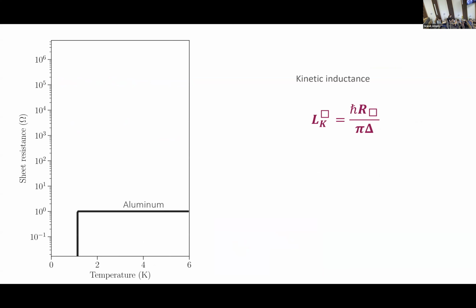Okay, now let's try to get a little bit of a sense about this quantity in terms of values. Here, what I show you is a huge scale of resistance, which goes very high, up to megaohms. It's a little bit ambitious, but I'm going to show you what it gives. So this is typically what you can expect for an aluminum film. It can actually be a little bit lower in terms of resistance, given the thickness you want. This is not a true transition, it's a PowerPoint line. And if you compute the inductance, you get something in the range of 0.01 to 1 picohenry per square. And what we have seen during this conference is that you can keep superconductivity to a very large disorder, up to a point where the superconductivity is destroyed.